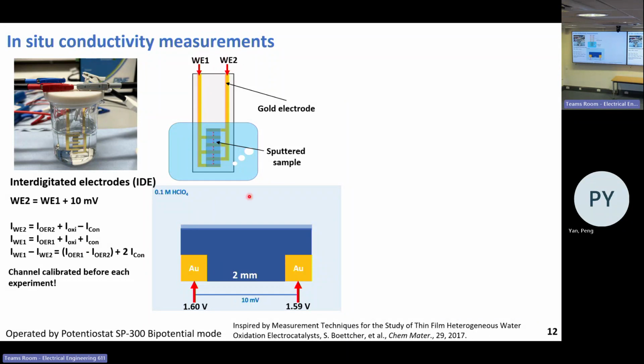And these 2 working electrodes are operating simultaneously with a bias difference of 10 millivolts. So the potentials applied here are to drive a catalytic process, and the difference in potential is to measure the conductivity.